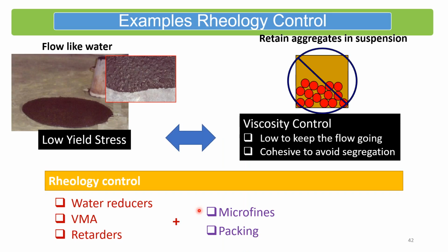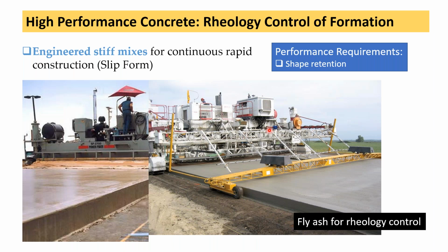So some examples of rheology control with fly ash. If I am to make SCC, self-compacting concrete, I need some mechanism to thicken my paste. Otherwise, the aggregate will not hold in suspension. They'll separate out. To get that viscosity control, to increase the stickiness of the paste, oftentimes fly ash is almost essential in producing a mix of SCC. High performance concrete, where I need the other end of the flow control, where I'm talking about slip forming of pavements. Here again, a concrete mix absolutely requires fly ash because it helps with the packing that I need, and it gives the mix that cohesiveness.